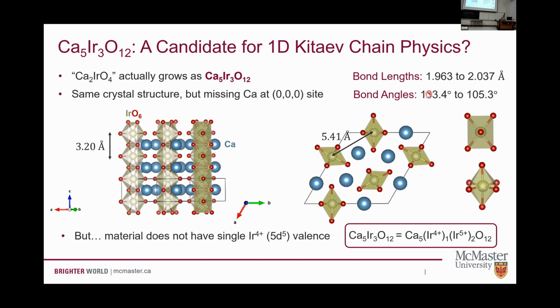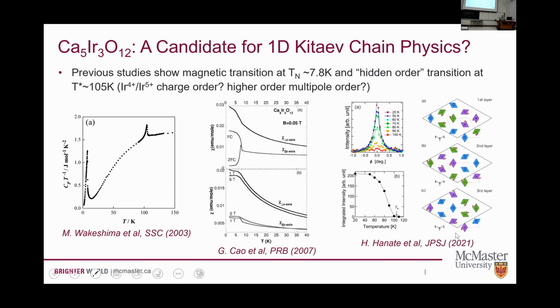Okay? The other complication, though, that we pick up when we lose some of these calciums is that now the valence is no longer this ideal 4+. So we don't just have iridium 4+, the 5d5 configuration that gave us these quantum spins. Now we've actually got 2 iridium 5+ ions for every iridium 4+ ion. So we have 1/3 of our iridium that have these quantum spins, 2/3 which are non-magnetic. Okay, so this does give rise to interesting physics in its own right.